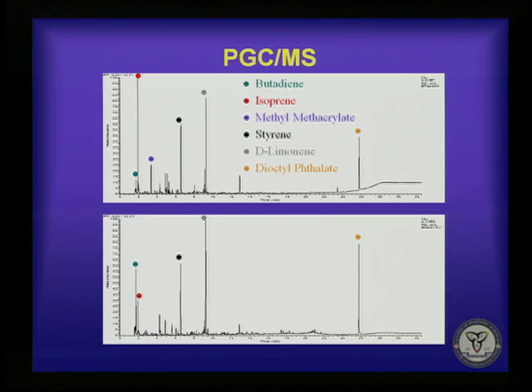And here are two chromatograms, and you can see, again, these were two tapes that we differentiated. The top one has more isoprene as compared to butadiene, and the bottom one has more butadiene as compared to the isoprene. The top chromatogram also has the acrylic component, methyl methacrylate, and they both have styrene, D-limonene, and a phthalate plasticizer.